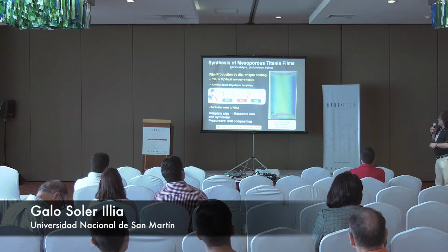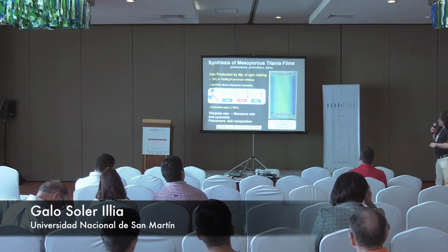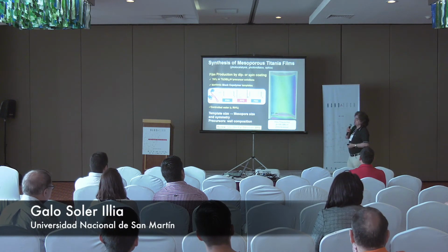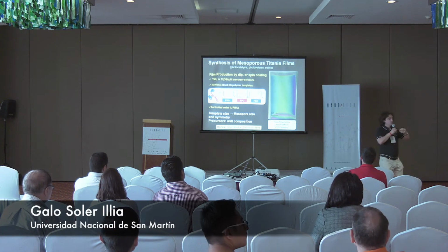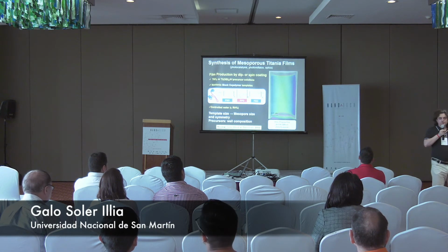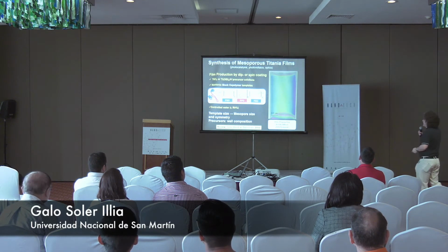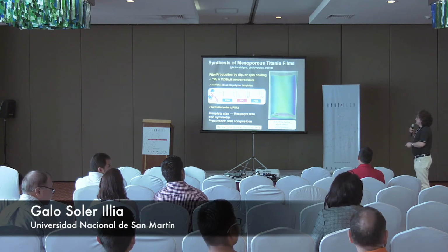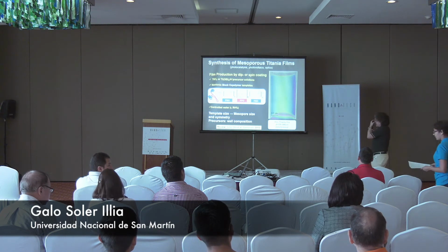ago, more or less. But by changing the N, the polymerization, the polymer length of this, you can go from spherical micelles to tubular micelles to very intricate designs. And you can vary, of course, the size of the molecule and then the size of the micelle very easily. And then you can control the mesopore size.